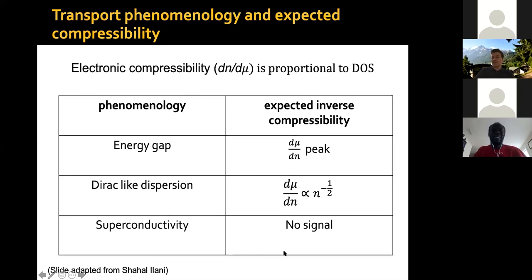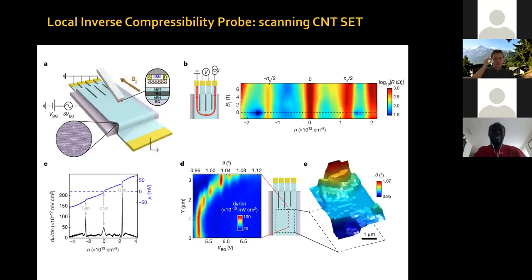Superconductivity does not manifest itself in the density of states of your system. Superconductivity leads to a gap, but it's a gap that is occurring always at your Fermi level. It's not a gap in the sense of a band gap, it's not a gap in your regular density of states. So in the thermodynamic sense, you do not expect a signal, at least to first order.